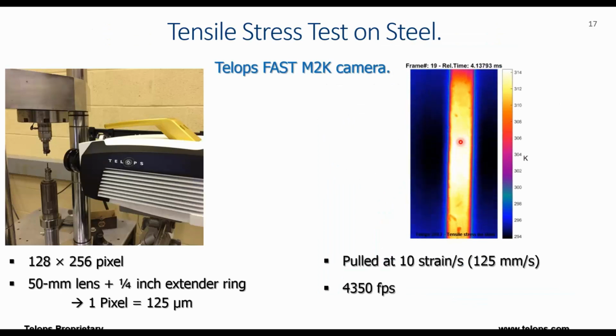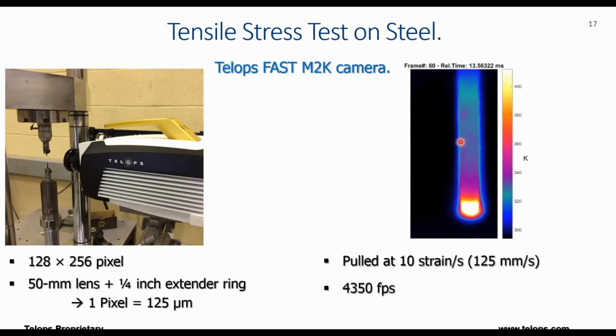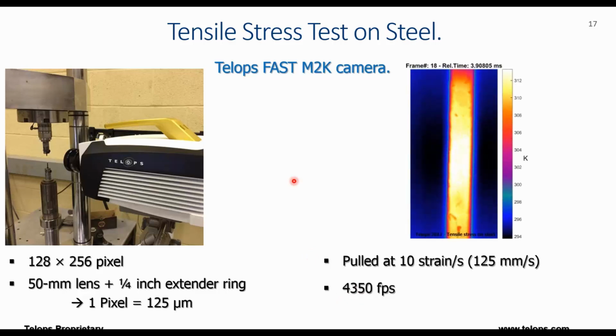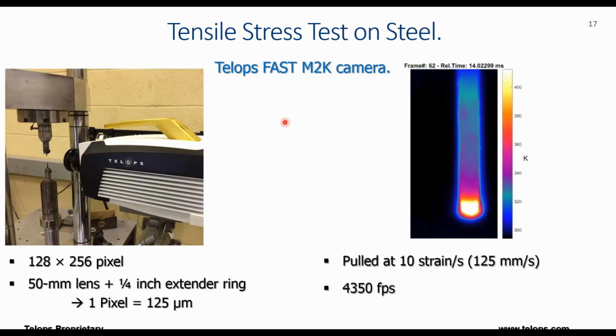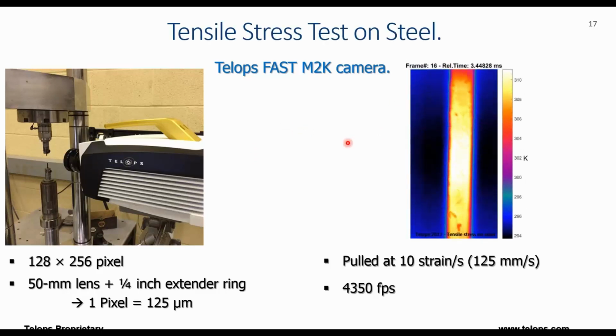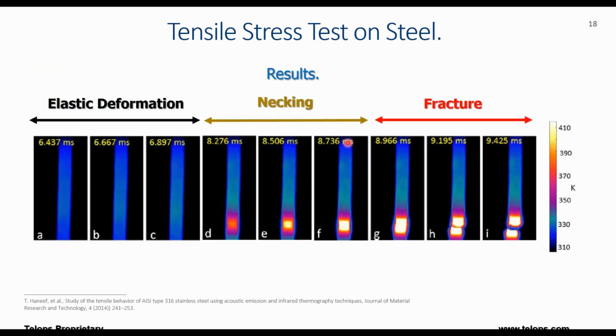This shows an example of a tensile test carried out on a steel sample with our M2K camera at 4,350 frames per second, and the video you see here allows us to visualize the result as a function of time. Time is shown here. And in the next slide, these are some selected images during the experiments, corresponding to different stages of a typical stress-strain curve. The time labels you can see here illustrate how fast the sample switches from one regime to the other. Here 1.3 milliseconds, here 0.2 milliseconds, highlighting the need for a high temporal resolution in this kind of experimental testing.